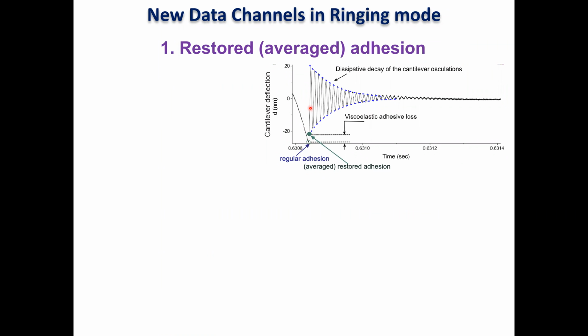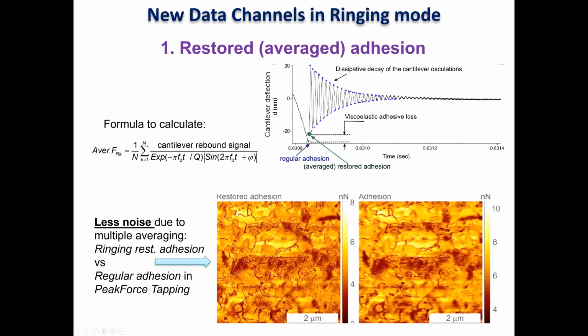And it's not only a measurement at one single point, but we measure the entire curve, using a fairly straightforward formula describing sinusoidal oscillations and decay. So we can use as many points as needed and get a very good signal-to-noise ratio. That's why it's called restored, and maybe even averaged adhesion, because we have quite a lot of different points. So this is an example of restored adhesion, and adhesion collected by regular subresonance tapping at